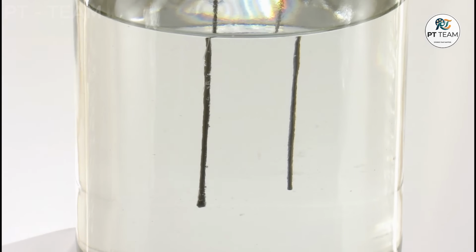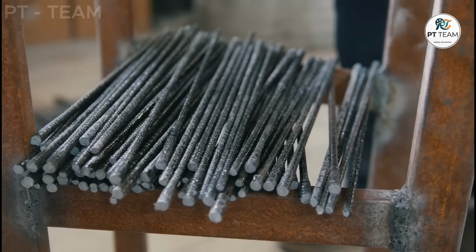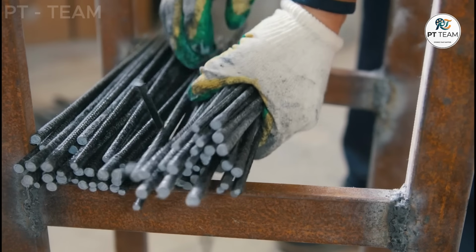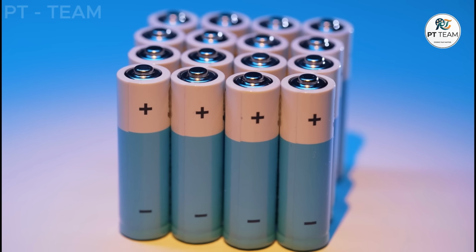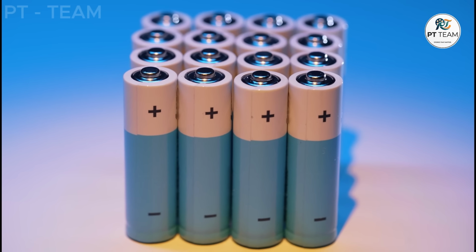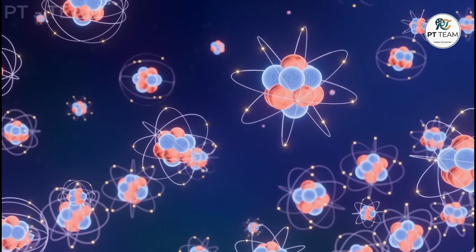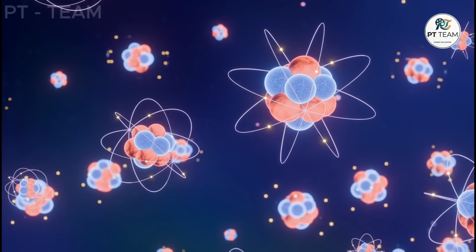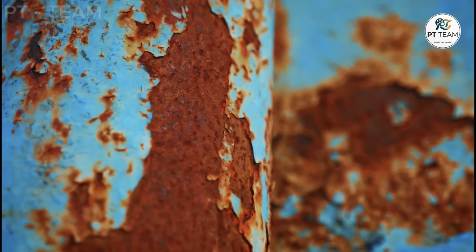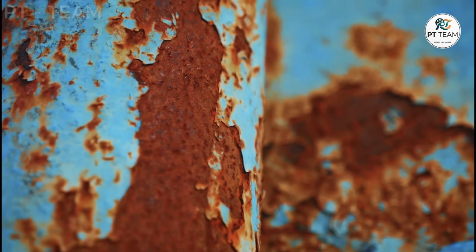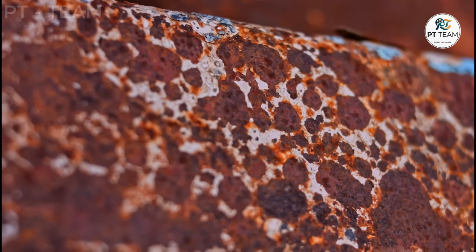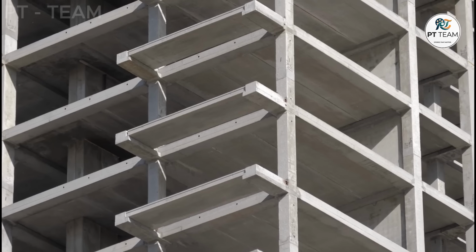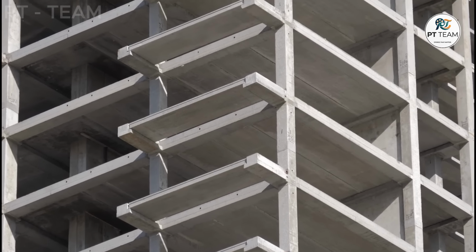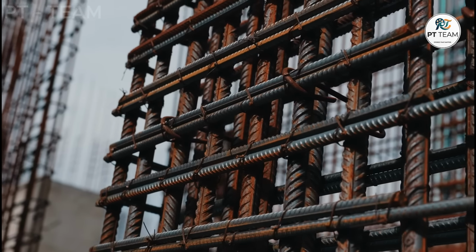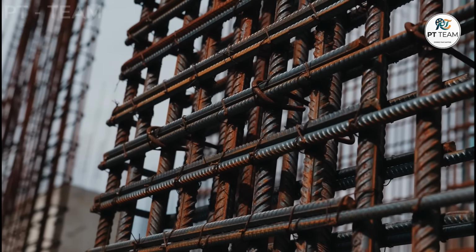The moment the passivation layer collapses, an electrochemical reaction begins. The steel reinforcement bar essentially becomes a battery. Different parts of the steel act as anodes and cathodes. Iron atoms lose electrons and dissolve into the surrounding moisture. They react with oxygen and water to form iron oxide. We know this common material simply as rust. But in the confined space of a structural column, rust is not just a cosmetic problem. It is a profound physical threat.